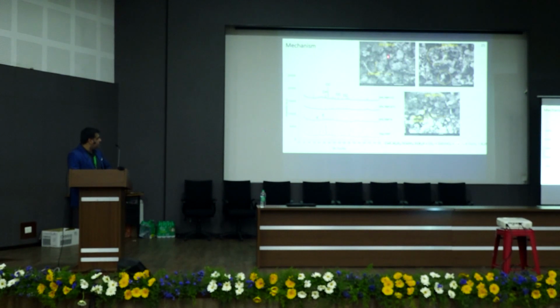So what our belief is, and it is still undergoing further investigation, is that due to the penetration of CO2, the ettringite can react with that, form alumina gel, aluminum hydroxide, calcium carbonate, and other compounds. And that's why we do not see much of ettringite. And due to conversion of ettringite to calcium carbonate, densification of the pore system happens, and that leads to reduction in shrinkage and improvement in compressive strength.